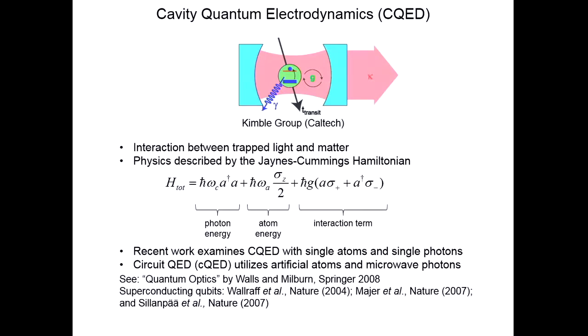Okay? Now, there are a couple of regimes to work in, but the interesting regime is where this coherent coupling rate, g, exceeds all of the loss rates in the system, right? We're never going to make a perfect cavity with perfect mirrors and light is going to leak out of the system over some time. But we'd like that process to be slow, and you want it to be slower than this interaction time, right? You'd like to have many quantum coherent interactions before the light leaks out, because that's the end of your experiment. The other thing that's important is that our qubits are never perfect, and that's why we're working on silicon. But we want a dephasing rate or an energy relaxation rate for our two-level atom, called gamma in this experiment, that's also slow. So good qubits, good cavities, small kappa, small gamma, and large interaction rates, large g's. That's what we want. g's called the vacuum-Rabi frequency.